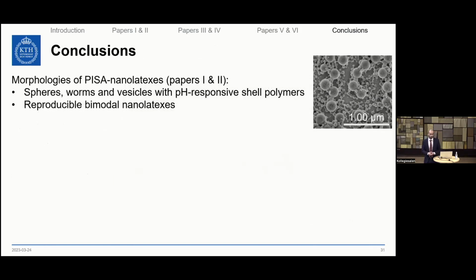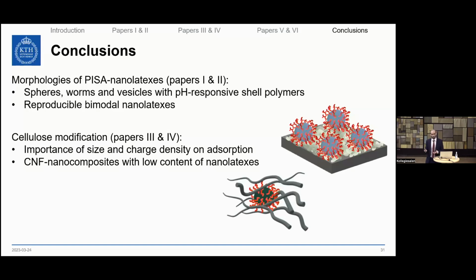So in order to conclude this presentation, we have studied different morphologies of PISA nanolatexes. We have prepared spheres, worms, and vesicles with pH-responsive shell polymers. And we also prepared bimodal nanolatexes in a one-pot fashion. And we studied the importance of size and charge density of PISA nanolatexes and how we can optimize these features in order to tailor the adsorption on different surfaces. And we use that information in practice in order to prepare CNF nanocomposites with low content of these PISA nanolatexes.